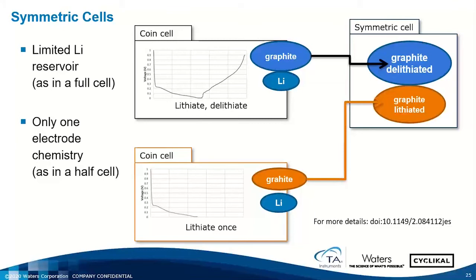So how do we make a symmetric cell? Well, we start with two coin cells. One coin cell we lithiate completely, and then we delithiate. The next coin cell, we just lithiate. So we take the lithium, put the lithium in, take it out, and in the other cell, we just leave it in. We take those two coin cells, open them up, and take the graphite electrode from one cell and match it with the graphite on the other cell. So what we end up with at the end is a coin cell with two graphite electrodes. One electrode is full of lithium, and the other electrode has no lithium in it. And all we're going to do now is rock that lithium back and forth.